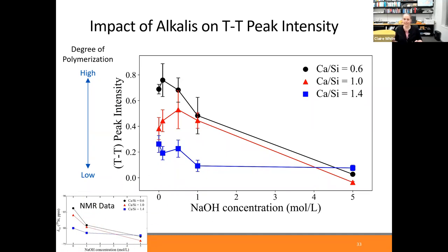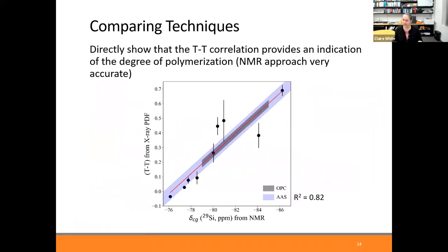We can actually look at local structure in terms of coordination, whether it's more coordinated or less coordinated with other silicate units, using this X-ray technique. When we compared with the NMR results, which is shown on this plot, there's a trend there. PDF analysis, pair distribution function analysis, is not going to be as accurate as NMR. But it was interesting to see that we could get this correlation between the two.